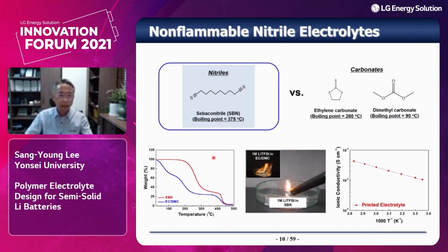Firstly, let me explain the non-flammable organic electrolytes. We are familiar with carbonate-based liquid electrolytes like this. However, those materials are flammable. So my attention was given to a different type of organic electrolyte, which is nitrogen-based. As a representative example, we have chosen sebaconitrile, which can provide a high boiling point, higher than 300 degrees C. And more importantly, the nitrile is non-flammable in comparison to the conventional carbonate one. It can also provide decent ionic conductivity even at room temperature. That's why we have chosen a nitrile-based electrolyte as the base electrolyte.